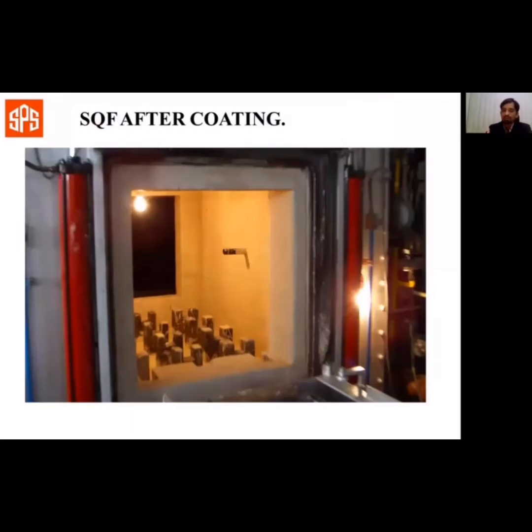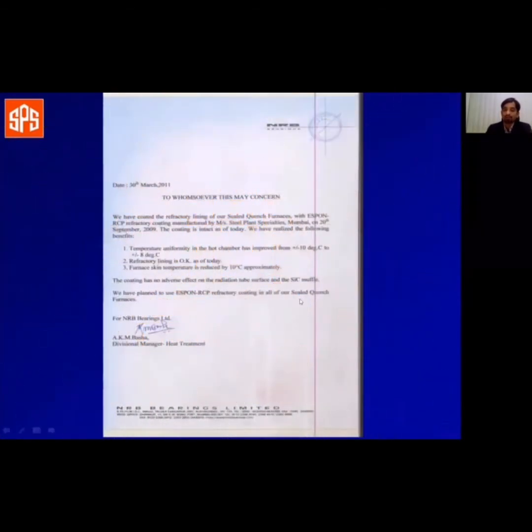The reason why I show you this small sealed quench furnace is because it is much easier to observe each parameter closely. And these are observations as given to us by the popular bearing manufacturer, NRB Bearings, after using the coating. They say that the uniformity of heat throughout the furnace increased by 8 degrees. Furnace outer shell temperature is reduced by 10 degrees approximately.